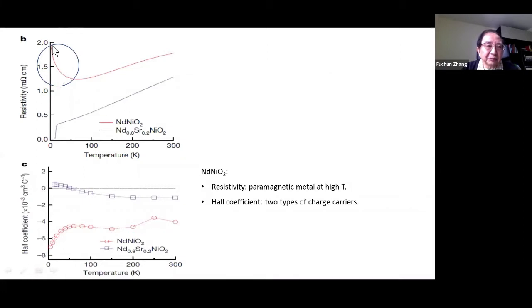This upturn, we will argue, is actually consistent with Kondo physics, because what Kondo proposed is that magnetic impurity scattering makes the resistivity turn up. The system here is not antiferromagnetic, even at the lowest temperature you can reach. So this is different from cuprate. However, doping makes a superconductor. This is similar to cuprate.